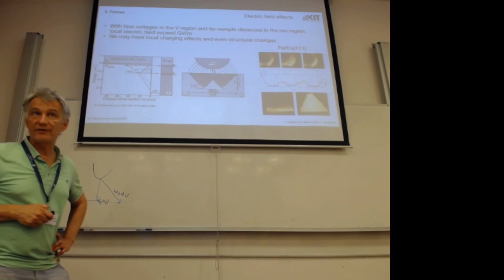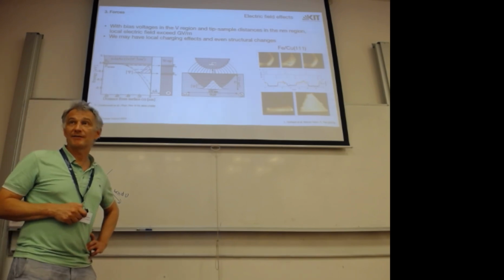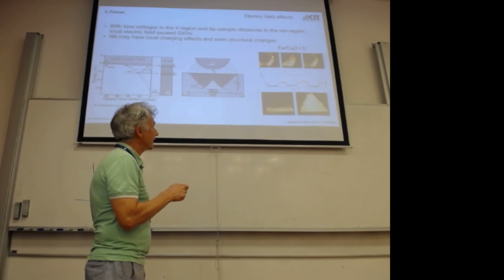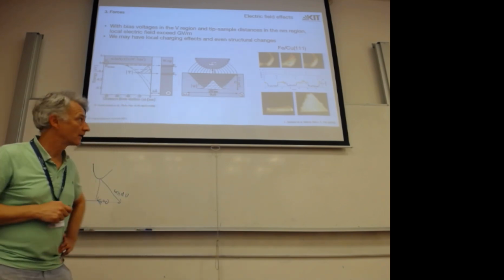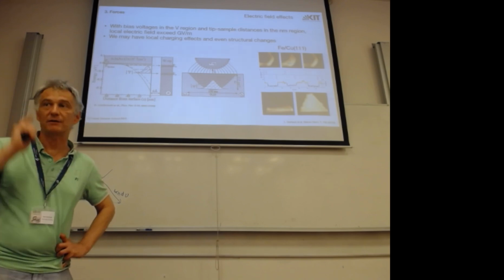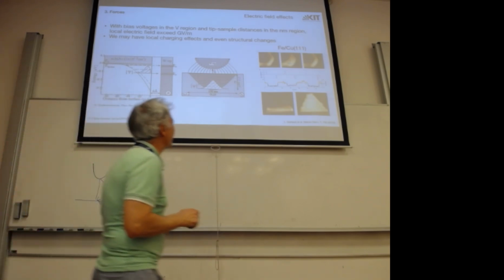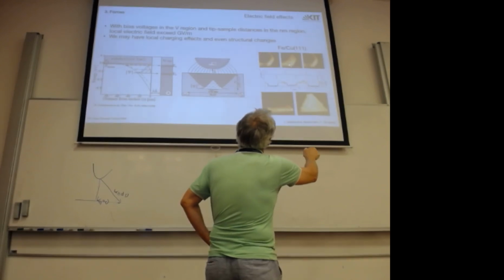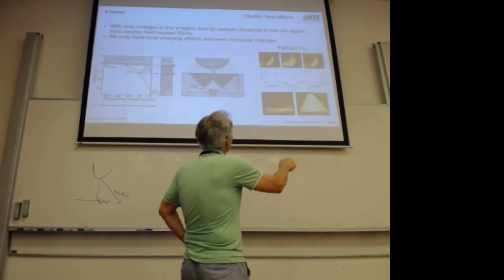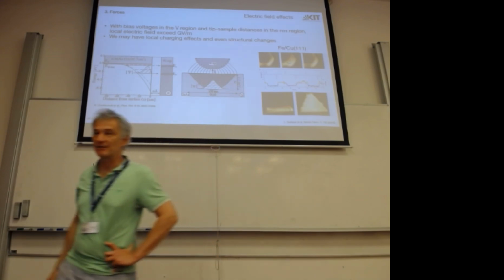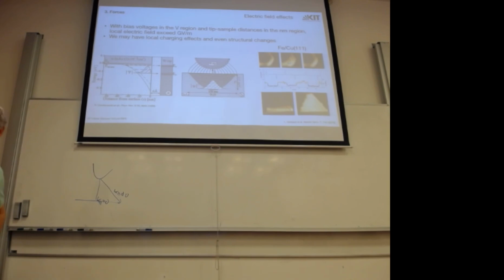The screening will now also affect these metals, although it's only an angstrom scale. It can switch. If I do the pulse here, I can switch BCC to FCC, and with another pulse with opposite polarization, I can switch back to BCC. So we can also change the modification of materials with that under certain circumstances in metals. Is there something written on those pictures? Yes, unfortunately, if I kill the light, it's better to see. There's a red BCC here, and there's a red FCC here. Or this island here is almost all BCC, and after the pulse, it's completely FCC. Okay. So you can induce a magnetic transition this way? Yes.